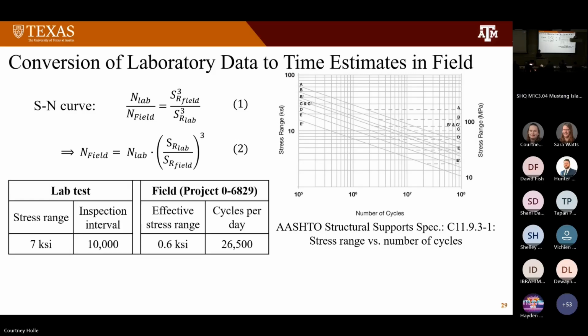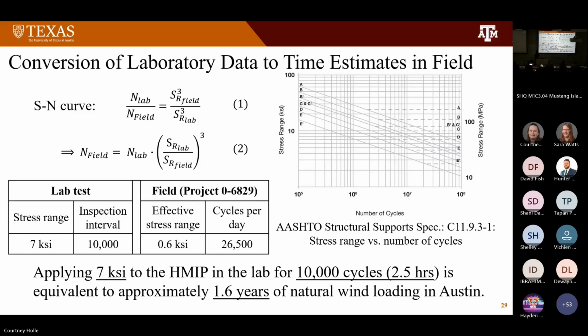So in our case, our lab test applies a stress range of 7 KSI divided by the effective stress range in the field of 0.6 KSI, cubed, and the result times the number of cycles in the lab equals the number of cycles in the field. This number of cycles in the field divided by cycles per day equals the duration of HMIP in the field. From the calculations, 10,000 cycles in the lab, 2.5 hours of testing, is equivalent to approximately 1.6 years of natural wind loading on an in-service HMIP in Austin.